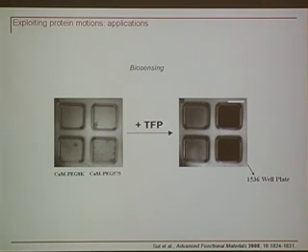And just as an initial demonstration of whether these materials might be useful in biosensing, we created 1536 well plates that contained hydrogels composed of the Calmodulin unit flanked by different molecular weights of the PEG unit. And in the case of the large molecular weight PEG units, which you may recall didn't undergo much of a shift in optics, we see some decrease in optical transparency, but it's not pronounced. Whereas in the hydrogels that contain low molecular weight PEG flanking units, we see essentially these spots turn black.